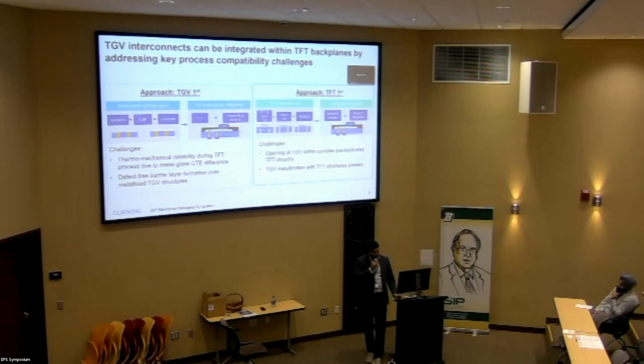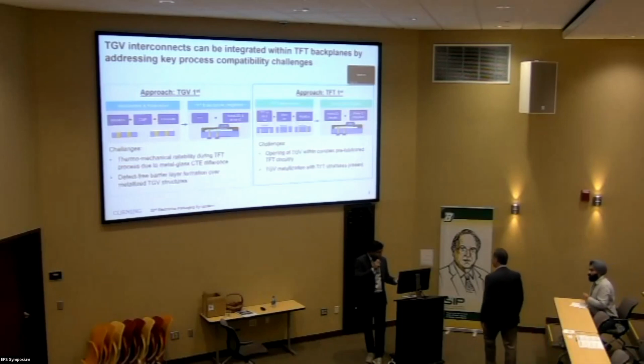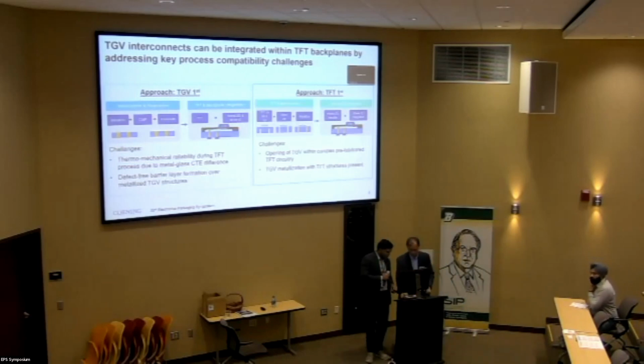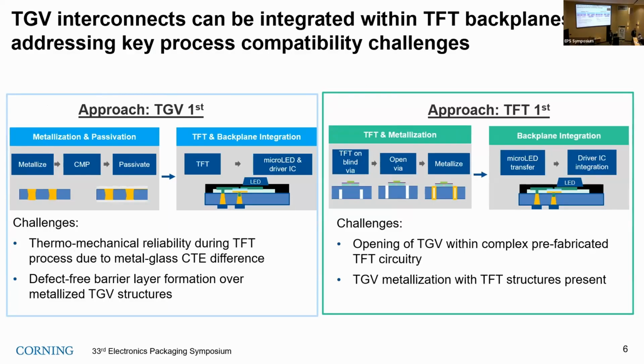So here you take a panel and create a blind via in it, and you have to know the depth of the blind via. So yeah, the second approach is the TFT first approach. You take a glass panel and create a blind via with a known depth, keeping the other side of the glass surface very planar and untouched.